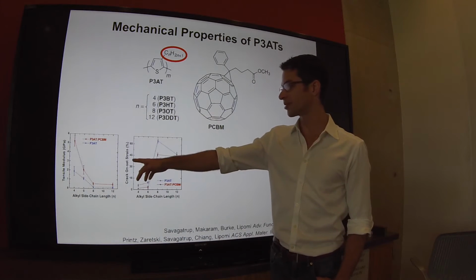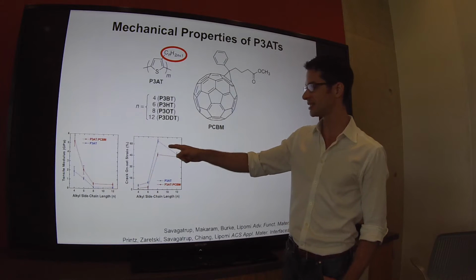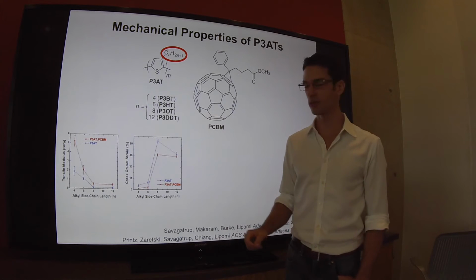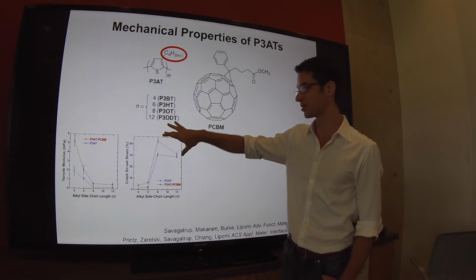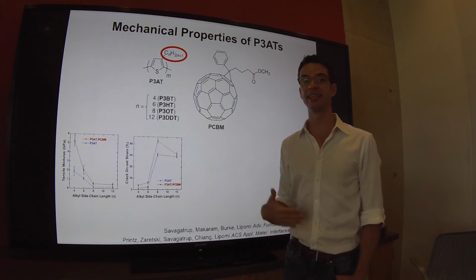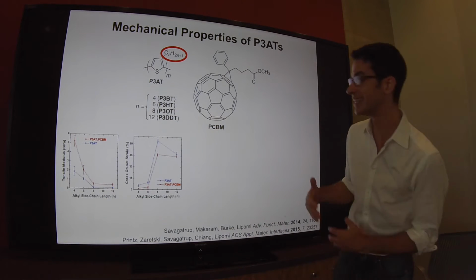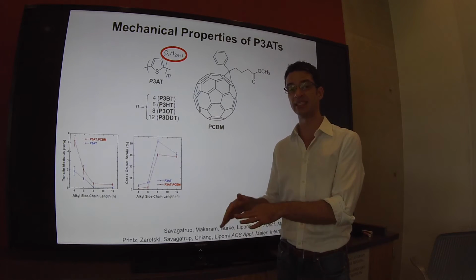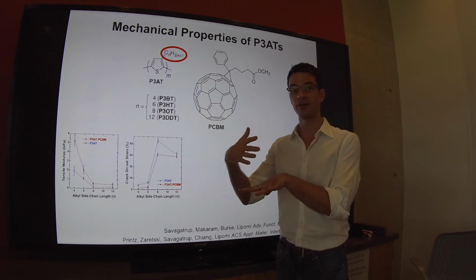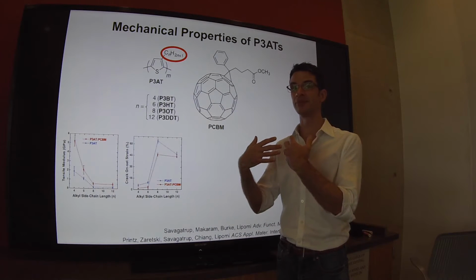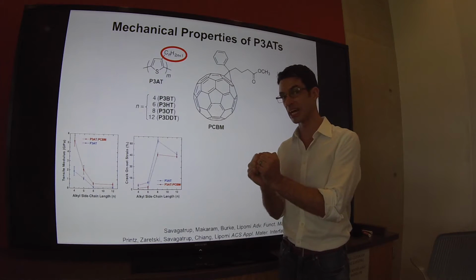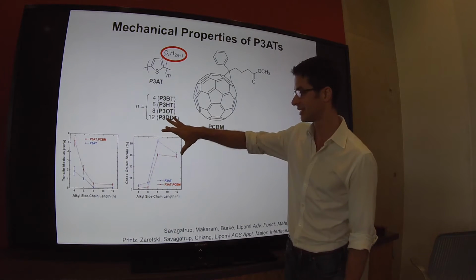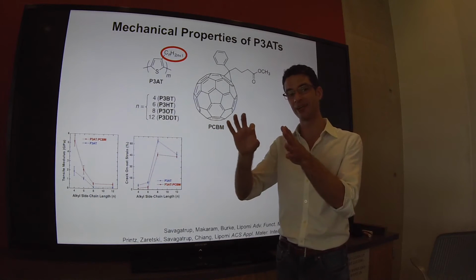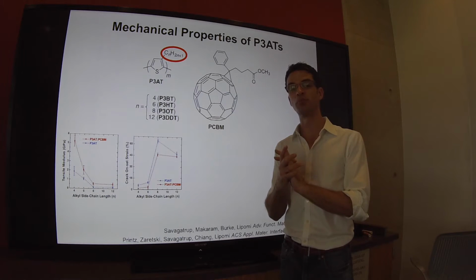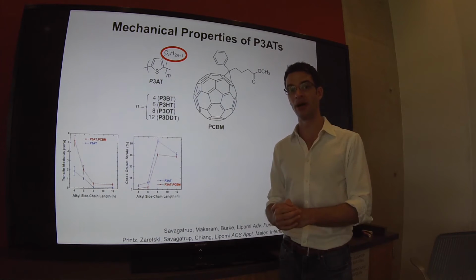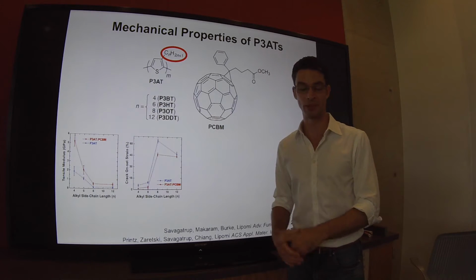The same effect is observed in the crack onset strain. So the material undergoes an increase in ductility and then a reduction in ductility. Here, we don't think this is actually a real effect of the material. We think this is because the adhesion of the film with the substrate actually decreases as you increase the length of the side chain. It becomes more hydrophobic. Its van der Waals coefficient goes down, so the adhesion is not as good, and therefore we think this is a result of strain concentration at thin areas and defects that one observes in poorly adhered films throughout the film on foil or film on elastomer literature.